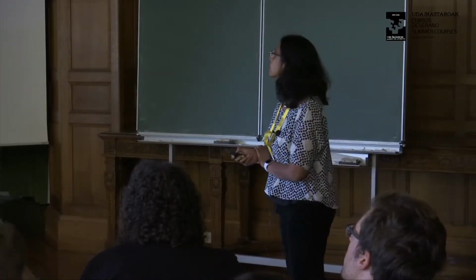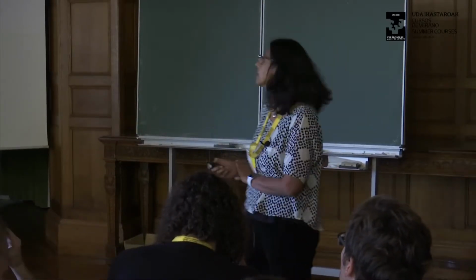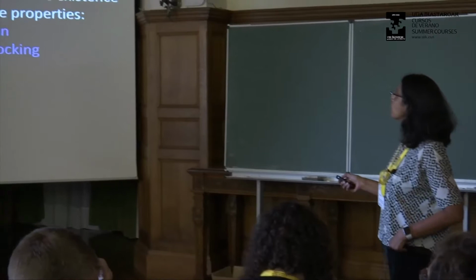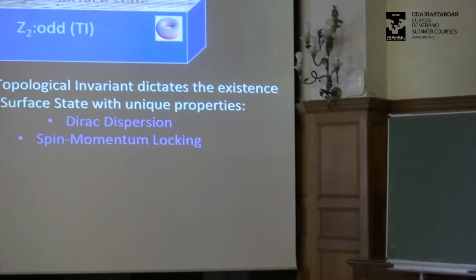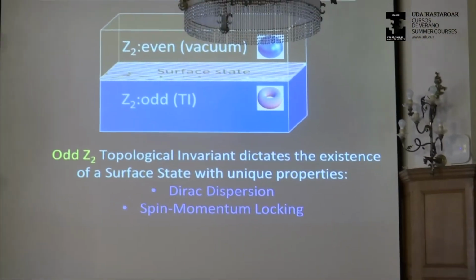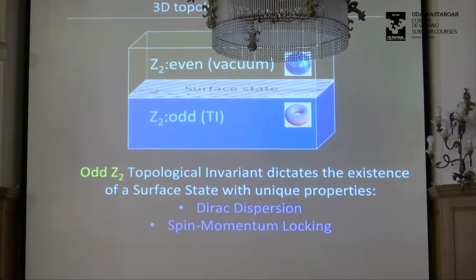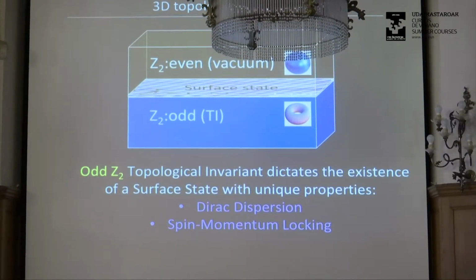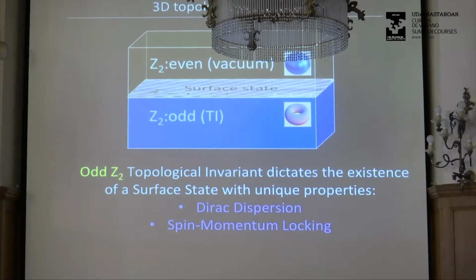So the third possibility is to use topological insulators. And as we know, on the surface of a 3D topological insulator, because you have vacuum, which is topologically trivial, it has an even Z2, you're bound to have these interesting surface states. And these surface states have exactly the kind of structure you need in order to get at least topologically non-trivial superconductivity.